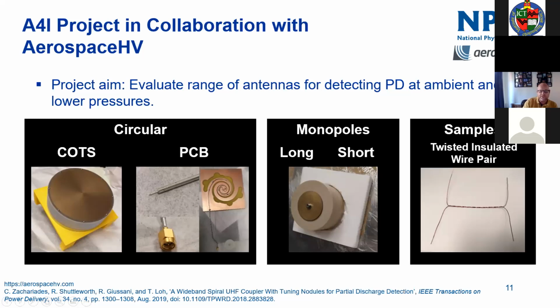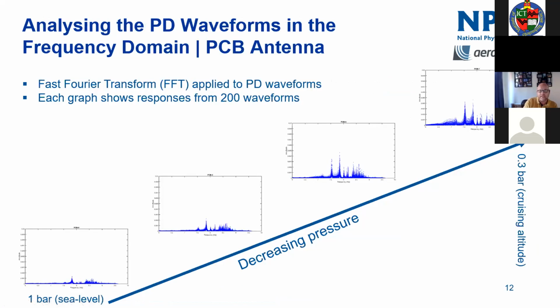Our test vehicle, which is the one we've done most of our work on so far, is this twisted insulated wire pair. And that represents the windings inside a motor core. But what that project did show us, is that there was definitely a change in the PD occurring as we reduce pressure. These show the antenna waveforms, so the signal the antenna's picking up, so they're not directly associated with voltages, etc. But you can see that the energy of these PD discharges is clearly increasing as we decrease the pressure. And we went down in this case to about 0.3 bar, which is a typical civilian aerospace cruising altitude.